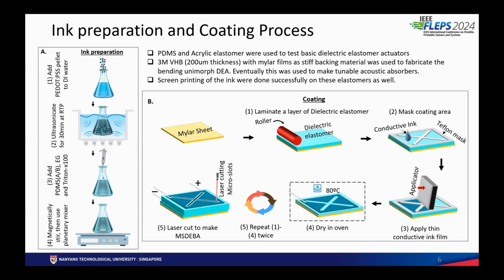So how do we make the ink? The ink is basically made of PEDOT:PSS. I will not go in depth because most of you are familiar with PEDOT:PSS, which is a form of conductive polymer. We form an aqueous form of this by ultrasonication, and then we mix PDMS part A, part B, along with Triton X, which is a surfactant, and ethylene glycol, which can enhance the electrical conductivity of this whole solution. After mixing it, we get a viscous ink.